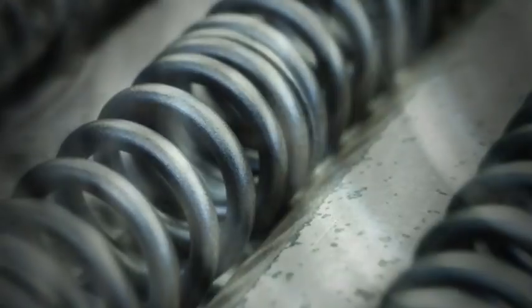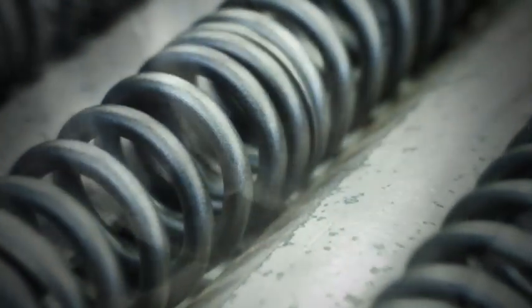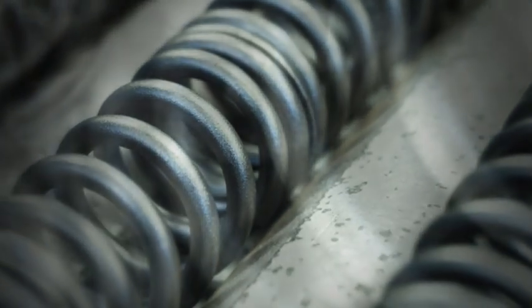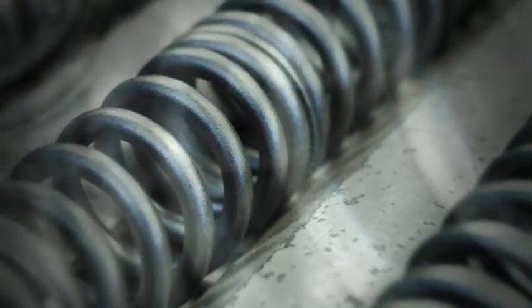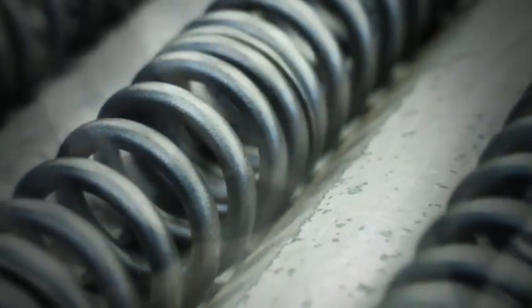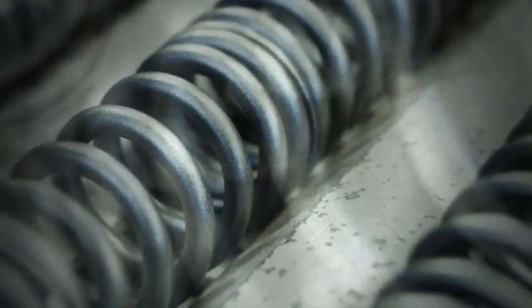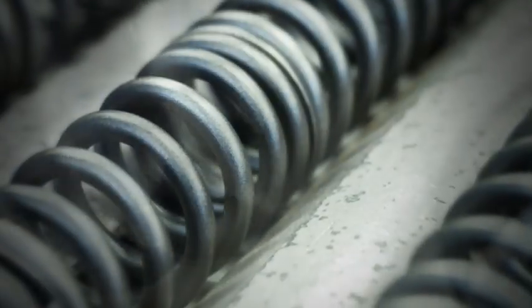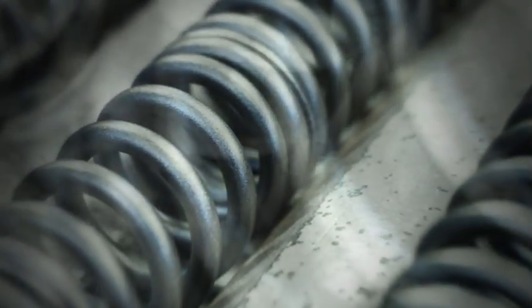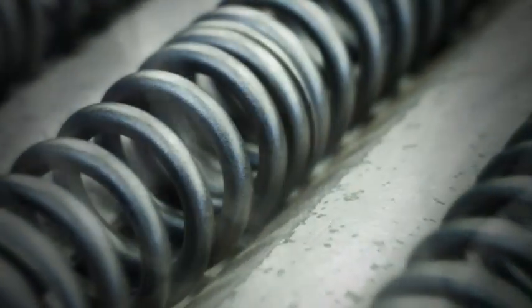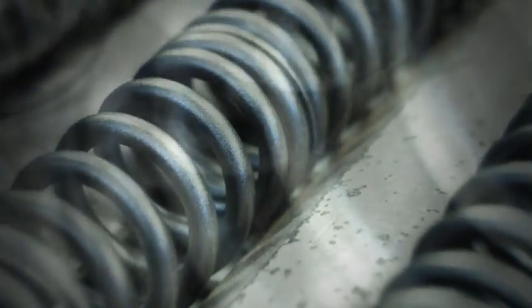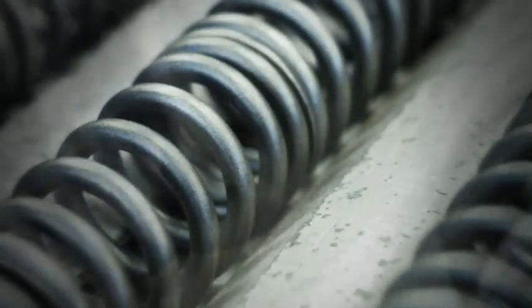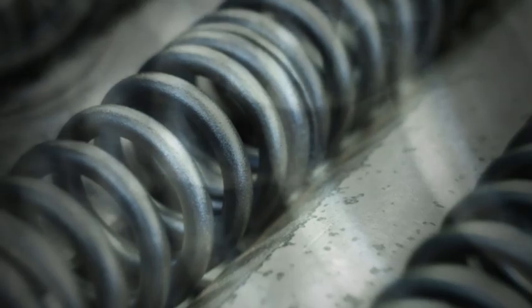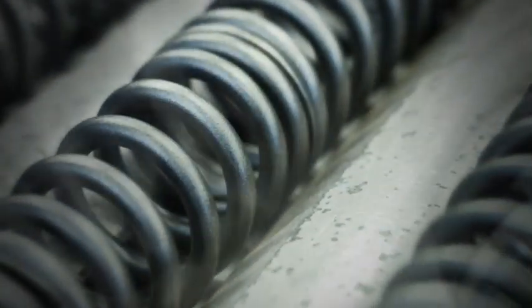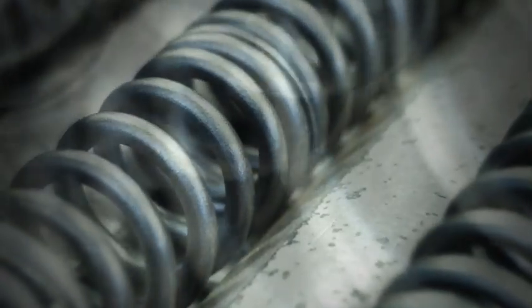Some springs are preset, also called scragged or set removed. A compression spring is compressed beyond its intended maximum operating position, sometimes close to solid height, under controlled conditions. The most highly stressed regions yield slightly. After release, the spring becomes shorter than it was before the operation and develops residual stresses that can improve stability and usable stress range. The customer receives a spring that has already experienced much of the initial permanent set that might otherwise occur in service.